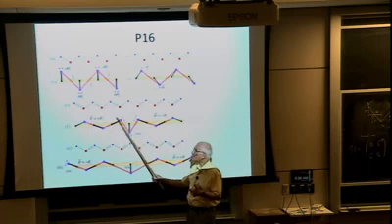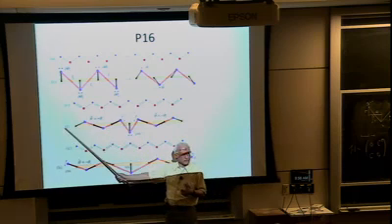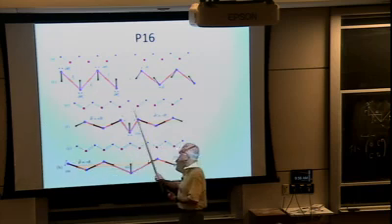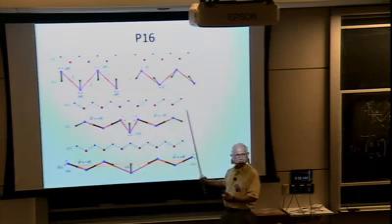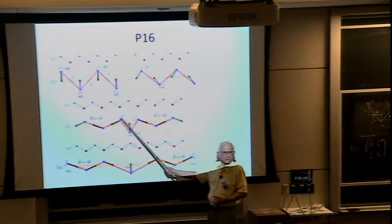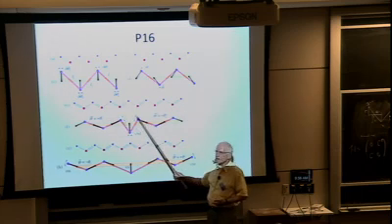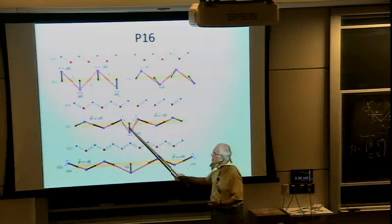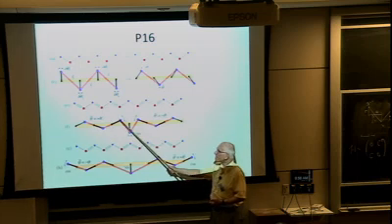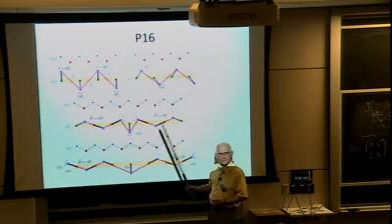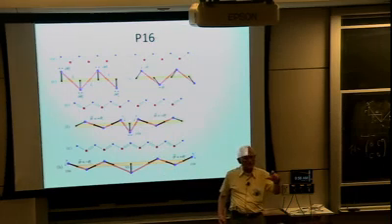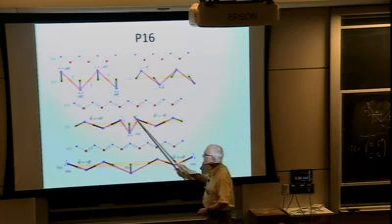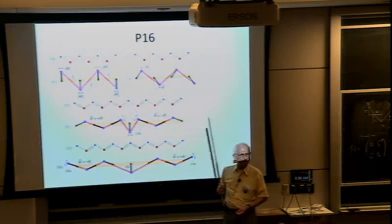So I know that if I allow it to decay with the calculation I've done for the free surface, every bond down in this direction is unstretched. I do the same thing here. Every bond in that direction is unstretched. And I have some amplitude, which I need to determine for each of those. So I have three different variables, the rotation of this site and the amplitudes of each decaying mode, and I have to use them to fix the length of two bonds. And I know I have no states of self-stress, so if we look at this thing, it turns out that there's one and only one zero mode there.